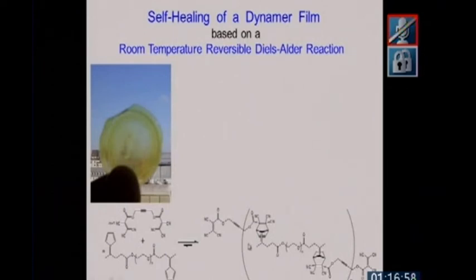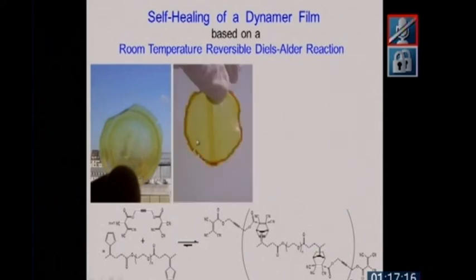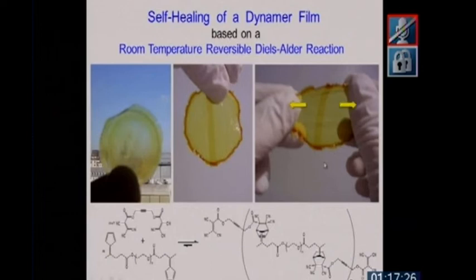Take this film, which has been obtained by a reversible Diels-Alder reaction. I don't want to get into it, but it's a reversible reaction which is fully reversible at room temperature. I want just to illustrate that when you take a film made from these objects, which continuously dissociate and reassociate, you can cut it in 2 and superimpose the 2 halves. You see here, and now you press it and heat somewhat, and you can now pull on it and it sticks again. That means that at the interface between the 2 films, you have now resealed, repaired the cutting, and new chemical bonds have formed, so that the sticking together is not a physical sticking, it's a chemical